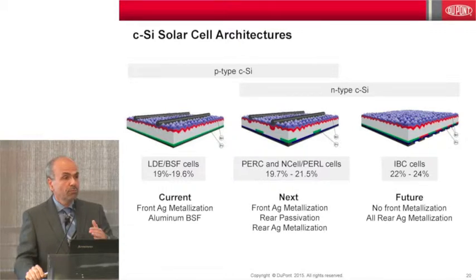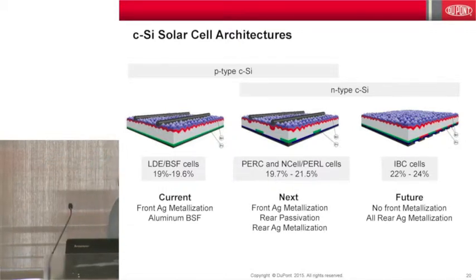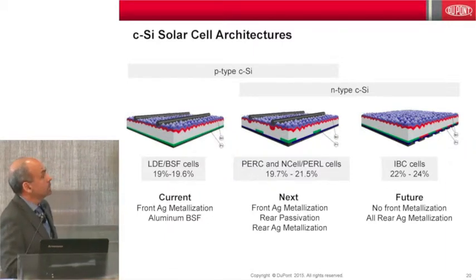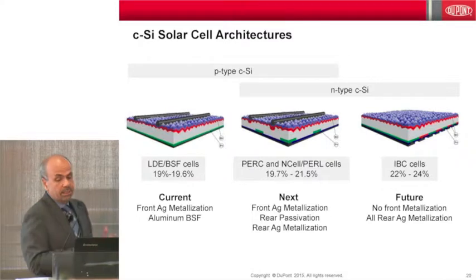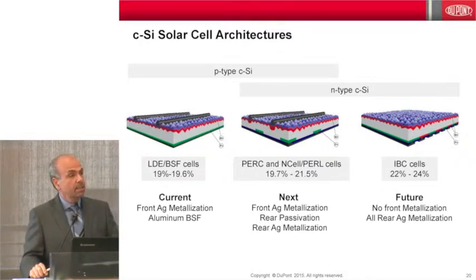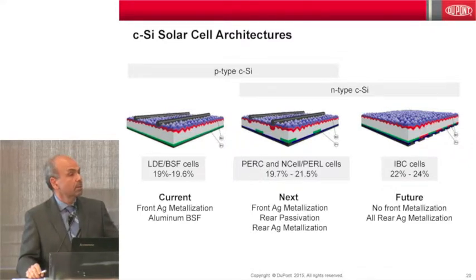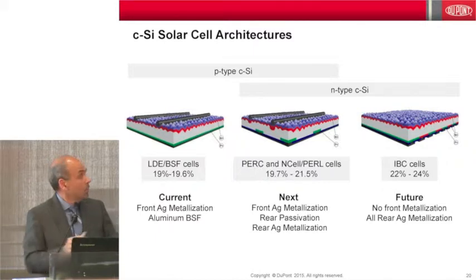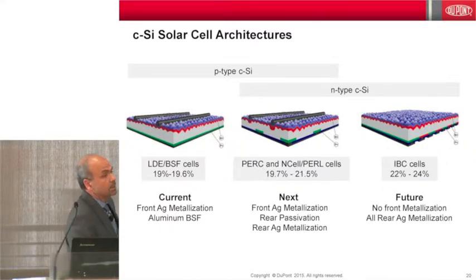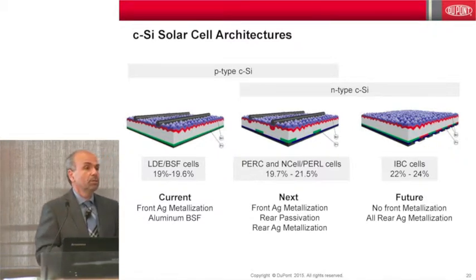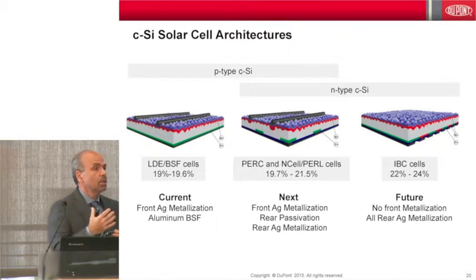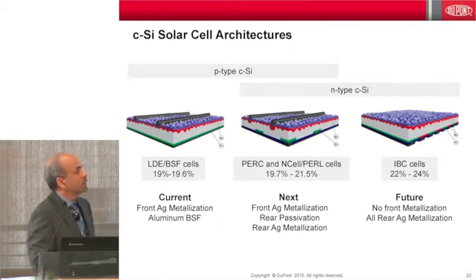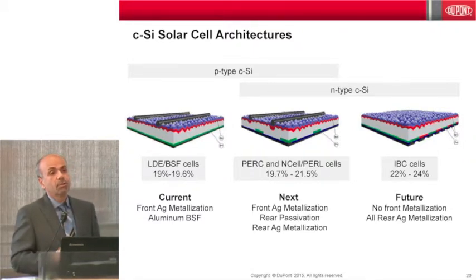architecture. And of course, the ultimate device structure, a device structure that has been pioneered by the group here in Stanford and then commercialized by SunPower, is the all-back contacted cell. And this is the ultimate cell that can deliver the highest efficiency in crystalline silicon. We are listing here 22 to 24, but efficiencies well above that are also possible. Of course, as you go from this device structure to this and then to IBC, the complexity increases tremendously. So the reason that the industry is not rushing through this is because we don't yet know how to mass produce these structures in a cost-effective way with materials that can deliver an attractive cost of ownership.